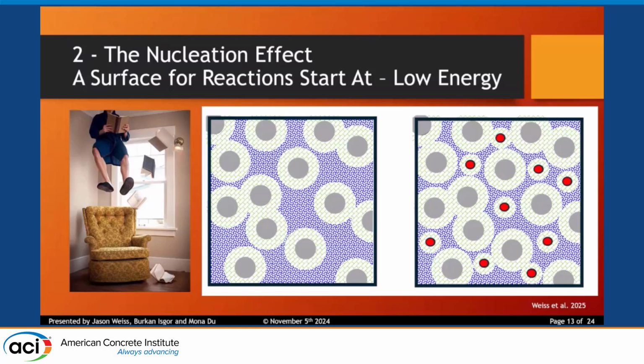So if you put in tiny nanoparticles, these can be limestone particles, calcium carbonate, these can be calcium hydroxide, these can be CSH. Those particles will actually start additional CSH growing that would have been growing through the solution process, right? And again, that's maybe 5 or 10% of the overall reaction. And we can promote this by actually adding some of these nanoparticles into the system. So some people may say, oh, nanotechnology, it sounds like it's space age. Well, people are doing it at commercial scale. They're adding these particles because they provide a nucleating agent that accelerates the overall reaction.